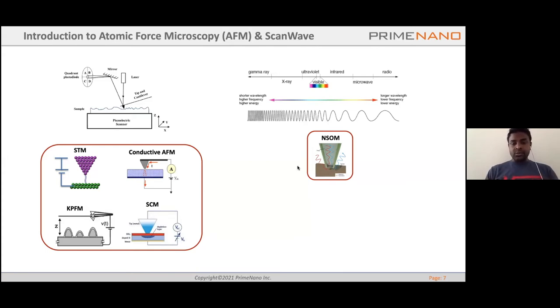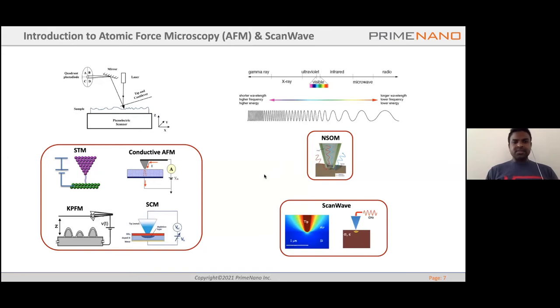So such as NSOM or SNOM, the scattering optical microscopy in near field, when you look at the optical response of the sample. In ScanWave systems, we use microwave frequencies through this AFM probe, and we look at the reflections from the surface. And the reflections represent the impedance of the sample. Further, you can also apply other electrical bias, like in scanning capacitance microscope, you can apply an AC bias, and you can also look at the electrical depletion width or the modulation of the depletion width as you apply the voltage.